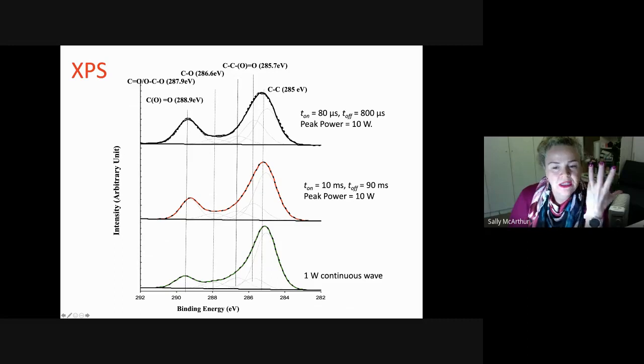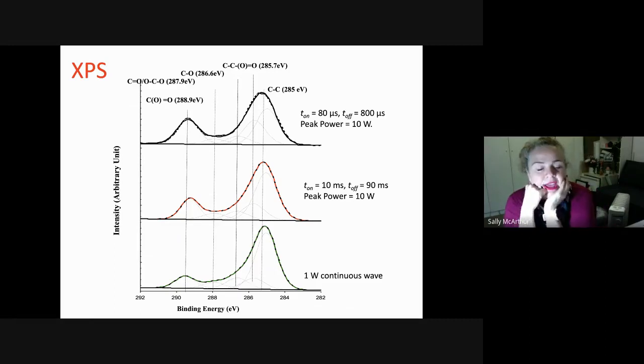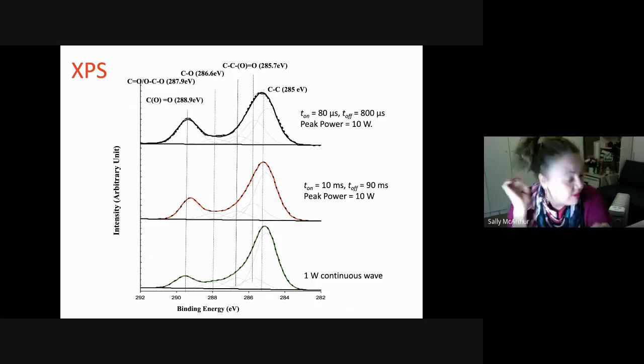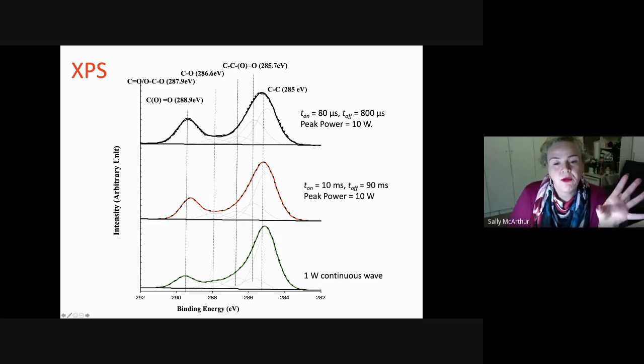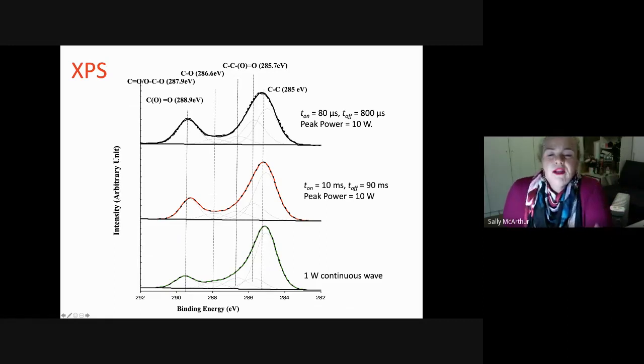If we start with our 1 watt continuous wave, so we're just depositing a film at 1 watt, it's very low power, and we get chemistry that you can see has quite a complex range of oxygen-containing species. And I have to admit, when you're fitting something like this, it's not the easiest thing to fit. There's not a lot of features there. You can fit absolutely down in the 289 range for your esters and ethers. And then you've got a beta shift down here that you can put in, and everything in between is more, how do you like to fit your data? But there are definitely more complex oxygen-containing species, some esters and some other groups in there as well.